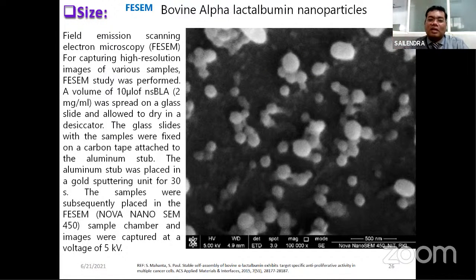If this carbon tape is not connecting to the aluminum stub at the bottom, the charge is not going to get transferred from the surface onto that aluminum stub. In that case, you won't be getting a perfect image on the surface. So that is a minor thing that you should know: this carbon tape should be attached to the aluminum stub at the bottom. Unless you do it, the charge dissipation is not proper, and whenever you are taking the image, it will be very blurred. Sometimes you can damage your samples when you are taking the images also.